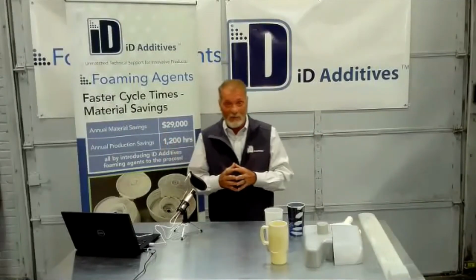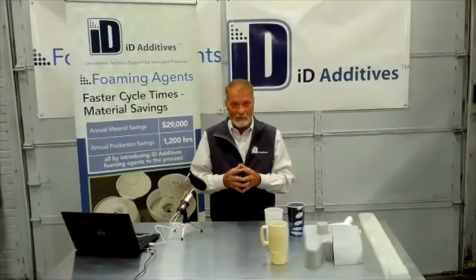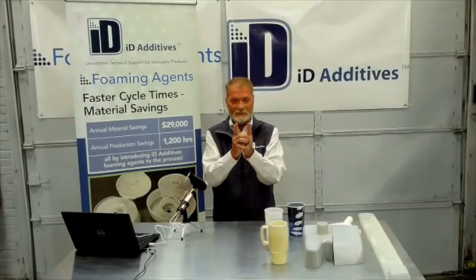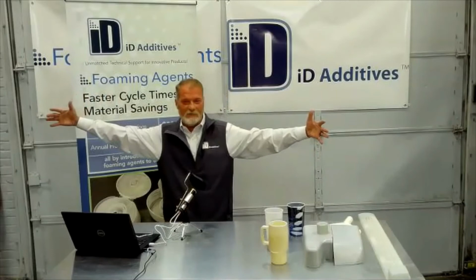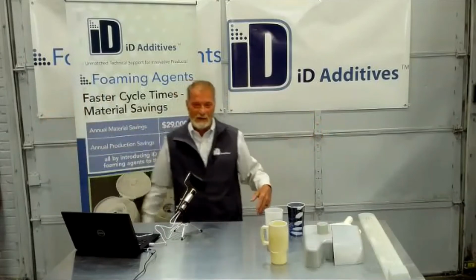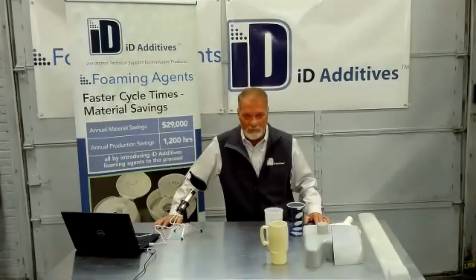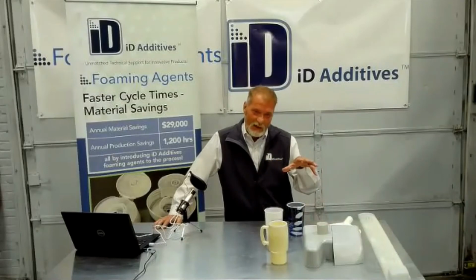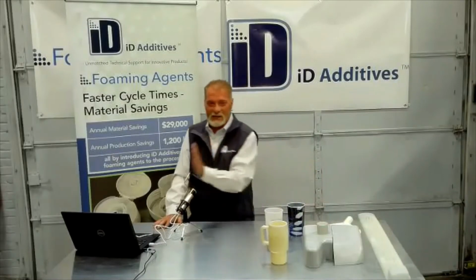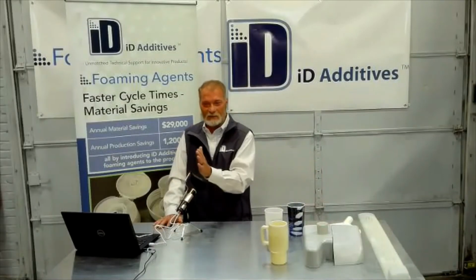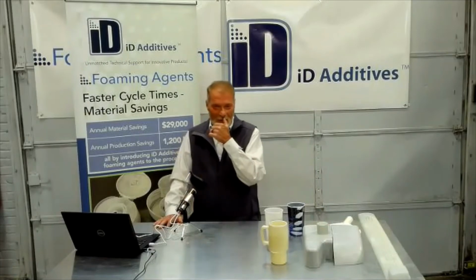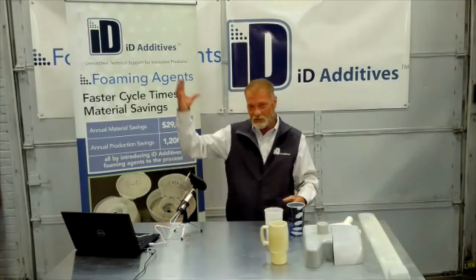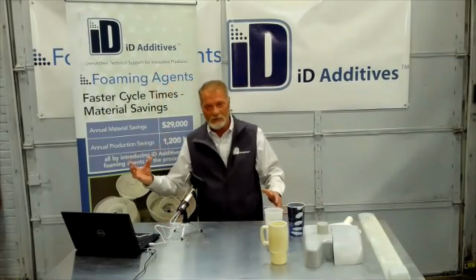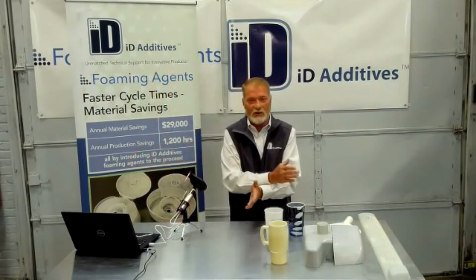Example: I ran a nylon part, a 2-inch shot, with about 15 shots in the barrel. They weren't getting any foam. To think outside the box, I moved the shot size up halfway up the barrel and moved the transfer 2 inches in front of it. All that did was reduce the amount of time that material spent before it got past the compression area.